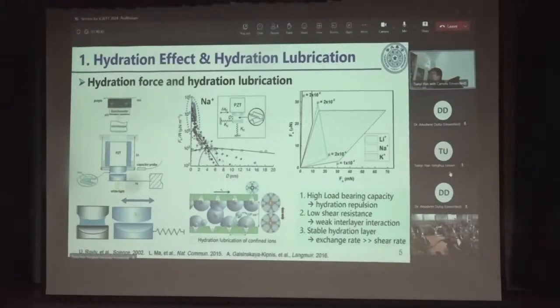Then they slid the two mica surfaces and found the friction is very low. This is the friction result. Here, this is the friction force, and the x-axis is the normal load. The friction coefficient is the slope of the friction force versus the normal load. The friction coefficient is as low as 10 to the power of minus 4 between the two mica surfaces, which is very low. They attributed the superlubricity to the weak shearing plane, and this phenomenon is called hydration lubrication.